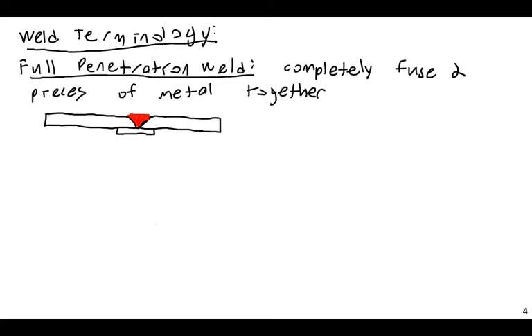Regarding what filler material to use — looking at table on page 16.1-125, Section J2.6, there is a whole table on filler metal requirements. For example, if you have A36 less than three-quarter inch thick, you have to use a matching filler material of 60 or 70 KSI weld material. Weld filler comes in thin wires and rods; you select a filler material compatible with whatever steel you're welding. That's a full pen weld.